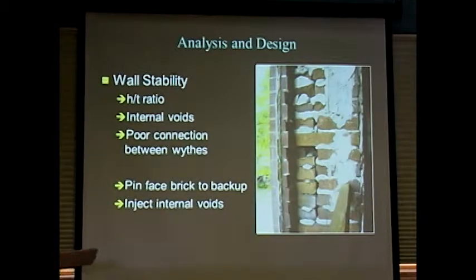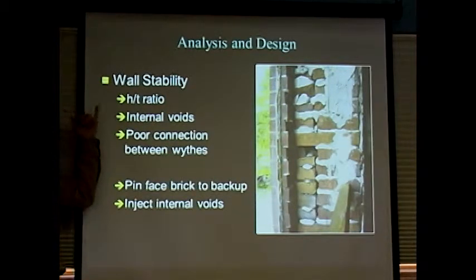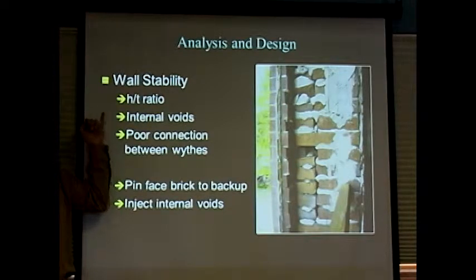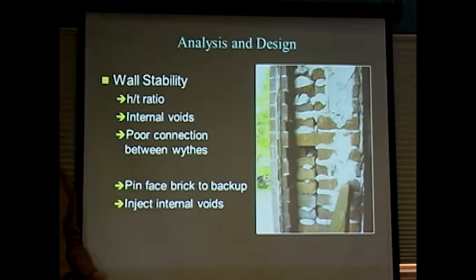And the best way I can explain this 18-inch thick wall was really as an 8-inch wall with two 4-inch walls kind of just happening to be standing there next to it. The main concern was how those four wythes of masonry were working together, because of the many internal voids and this rather poor connection with the blind headers, sometimes there, sometimes not, maybe not grabbing on as well as we need to, and really made worse by the decision to have these walls spanning really 40 feet between connection points.